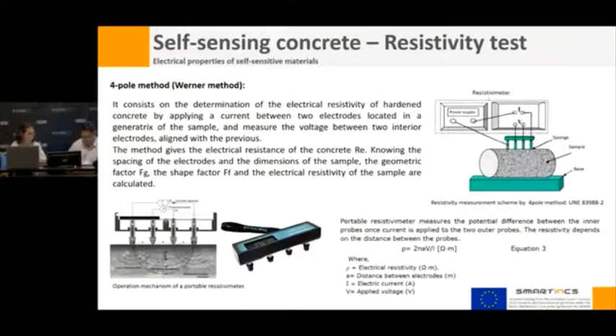The four-pole method, or Wenner method, is slightly different. In this case, the resistance is measured by a device that has four electrodes, and the current is applied between the two outer electrodes, and the voltage is measured at the two inner electrodes. Once again, with the resistance value, we convert it to resistivity. In the market, there are also portable resistivity meters that measure this parameter directly, and they are used mainly for quality control tests.